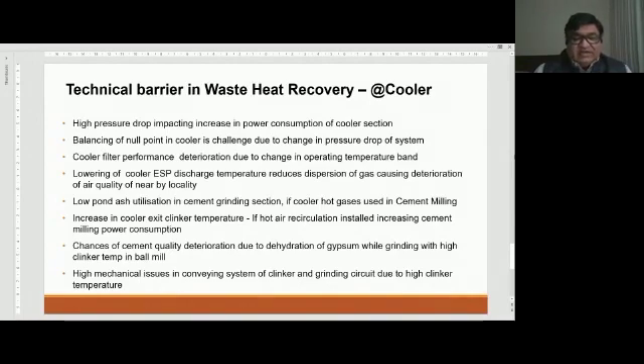We have also seen that the cooler filter performance, especially the ESP in the cooler, gets deteriorated because your temperature band keeps on changing whenever the stop-starts or problems come. Second, we have also seen sometimes that particles also go to the cooler, which creates a wear rate in the ducts, which increases the holes and all the deterioration in the ducts, which can impact the performance of the filter also.